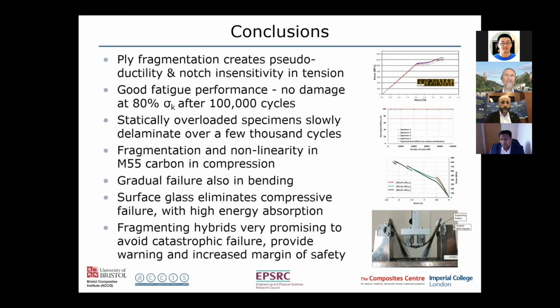So it certainly will change. Those damage mode maps depend on all the parameters. So it's a bit hard to say exactly how they depend on the modulus. What's most important really is the failure strains, the relative difference in the failure strains. The modulus, of course, does affect that as well. And the ply thicknesses are important. So generally, when you have a higher modulus fiber, then you have quite a different failure strain. Typically, failure strain reduces on these high modulus fibers. So that probably has a bigger effect than the modulus itself. But there's a lot of potential to design and tailor these materials depending on the particular properties of the fibers you want to combine.